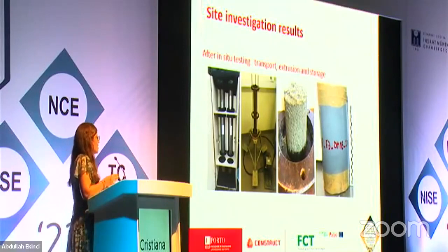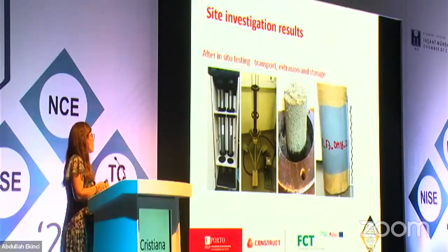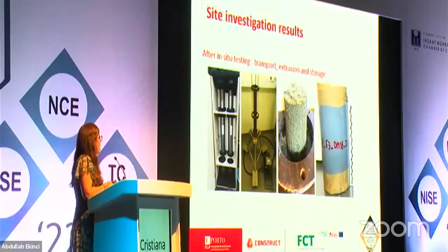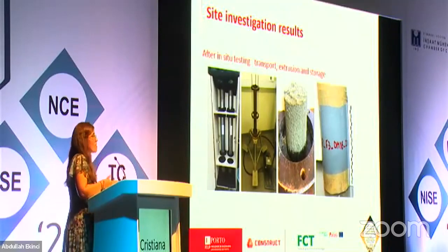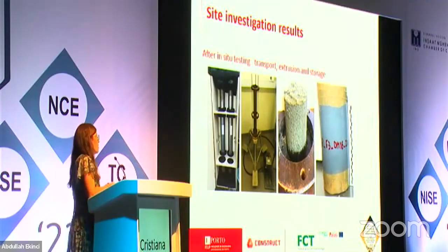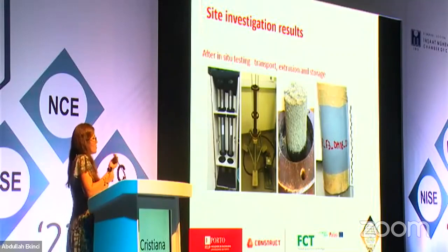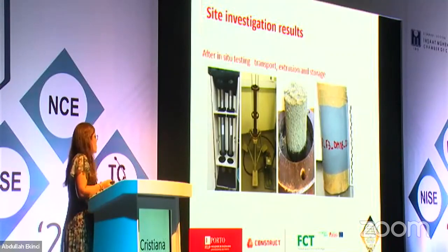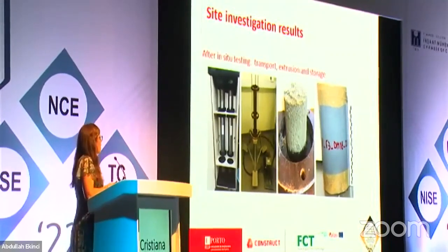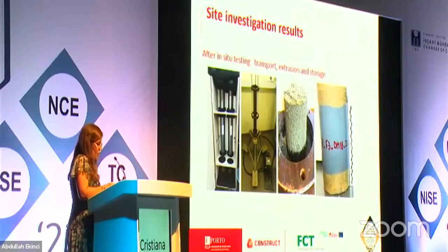Let me remind you that Lisbon, or this area very close to Lisbon, is about 3 hours drive from Porto, where we were going to do the tests. And then we wanted to make sure that the samples were carried and transported always in a vertical position as they were in the field, because if you leave it in the horizontal position and it's a loose sand, obviously it's going to create a void, and that would never recover the original structure. So following that, extrusion was also vertical, which is not so common.